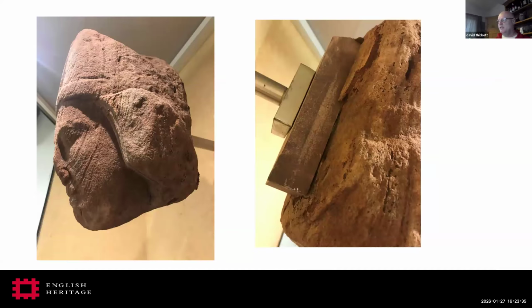And then the final thing I'm really going to talk about is stone deterioration, which could easily take up the whole of this webinar. But the presence of soluble salts can be really problematic. And this is a sandstone head from Furness Abbey. And you can see the loss of detail that we've had with this. And as I said, the British Museum, 1970s, they were drilling their stone objects to analyze how much soluble salt was present in there. That's fine for a building, or if you've got a big break surface. Kind of not okay if you have to drill the sculptural surface. And what we've been doing is looking at poulticing as an alternative.